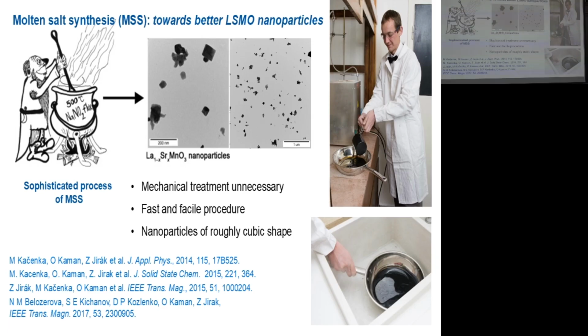We were happy, and we studied these particles, and we revealed some interesting features there. Actually, these particles were extremely different to the sol-gel particles, to the particles prepared by the first method I mentioned. And maybe from the practical point of view, the major issue was that the magnetization of these particles was strongly reduced. The magnetization was reduced not only compared to bulk samples, but also compared to the sol-gel particles. We really spent a lot of time, and maybe a lot of funding, while analyzing these particles and doing some fancy studies. It brought many papers, and maybe the material was not worth that from the application point of view, but it was really fun.